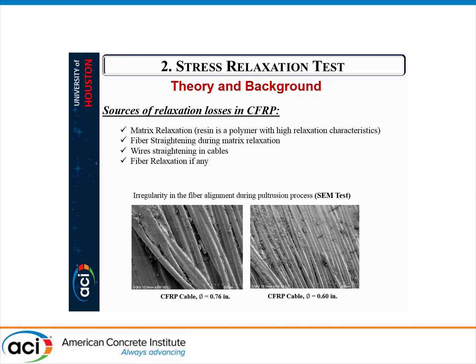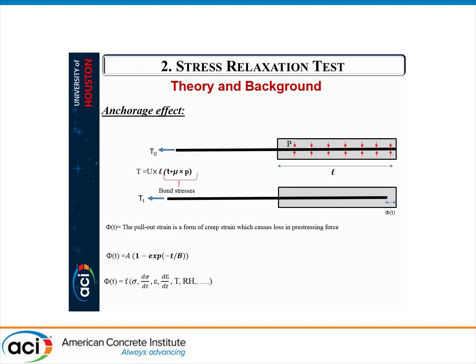After applying the load, due to time, these fibers start to straighten by flowing through the matrix, and this process causes further loss of load or stress. And we have the wire straightening in the case of twisted wire cables, and also fiber relaxation by itself, which in the case of carbon fibers is known to be close to zero. And these SEM pictures show the misalignment in the carbon fibers in two types of CFRP with 0.76 inch and 0.6 inch diameter.